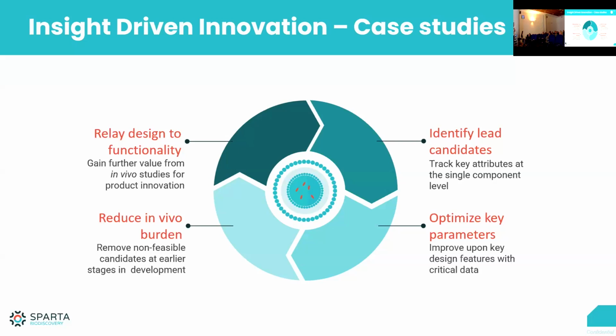And what's very frustrating when we hear from a lot of people is that the formulation that I made last week worked really well, and then the one I made today doesn't work very well, and I don't know why. And this is really where this heavier investigation can prevent you from doing a lot of work that is not going to be necessary, because maybe within our analysis on SPARTA, you could have told that the formulation which you made today had a mistake in it, and we could have made it again, rather than waiting 2 weeks for my cell study to be done. So there's a lot of benefit here in this deeper investigation at an earlier stage of the process.